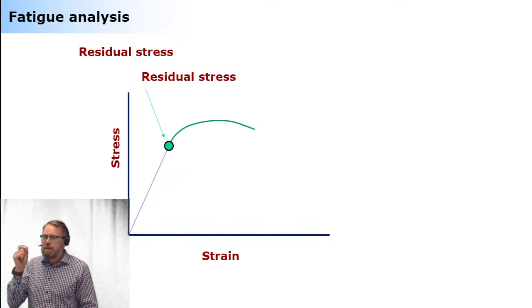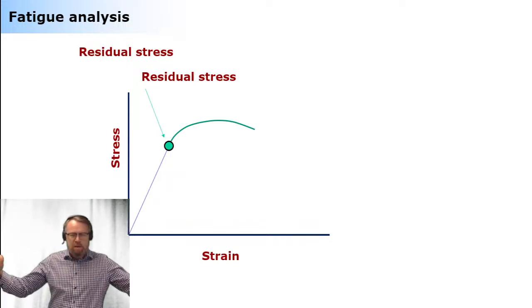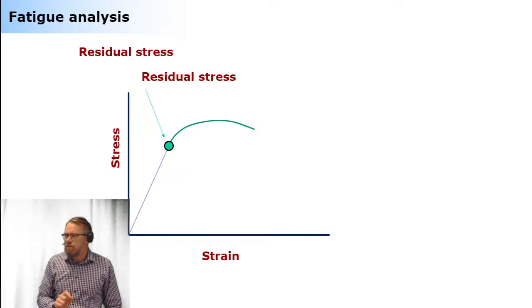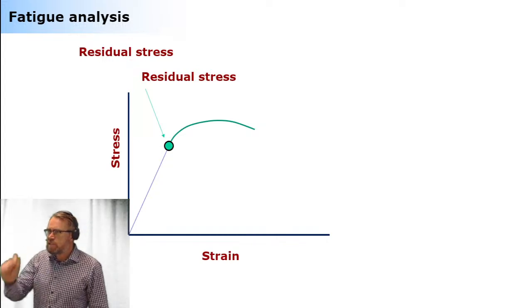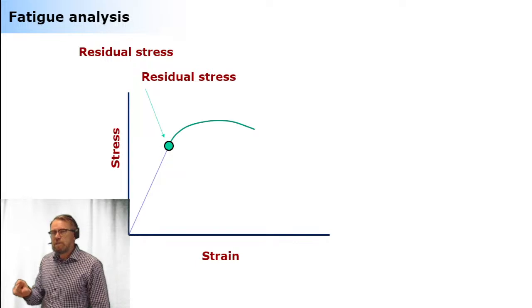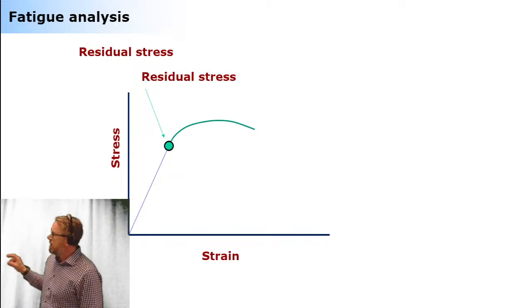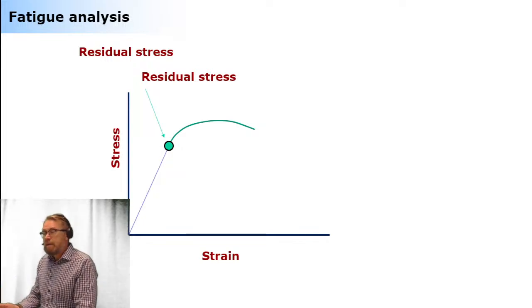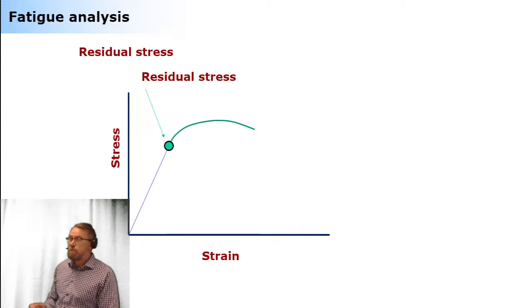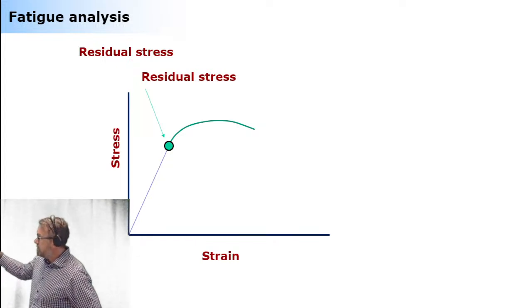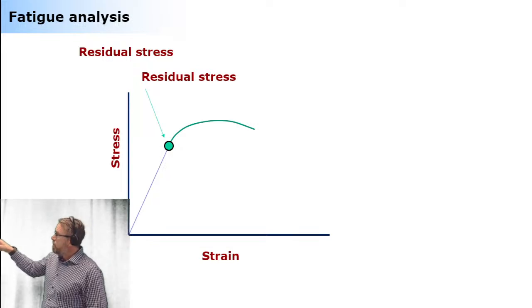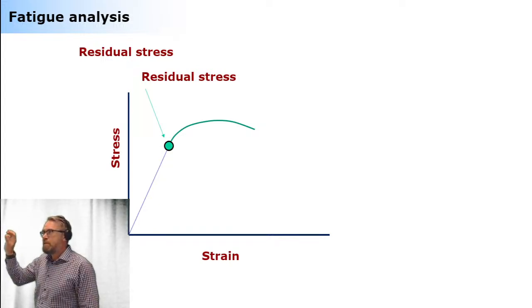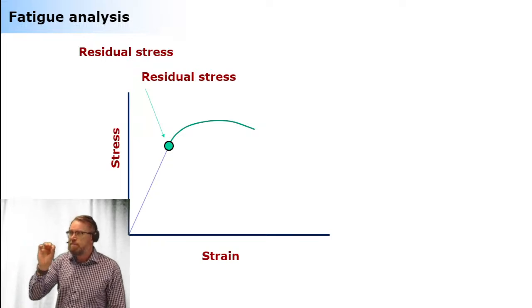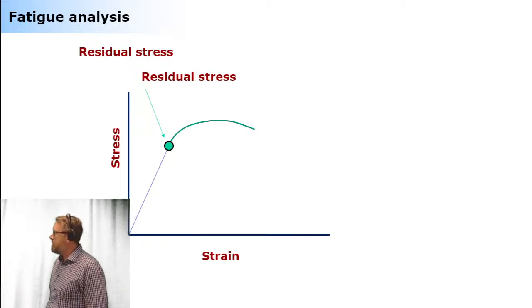Now, very locally, again, let me emphasize, very local, when you're not looking at the structure as a whole, but you look at the minor detail in your structure. Due to the welding process itself, because you're introducing so much heat when you're welding components together, you have very high residual stresses. Actually, in a corner, this linear behavior turns out to be non-linear behavior. And this non-linear behavior is very bad because, let me rephrase it, if you step left from the point that you can see, there's a green spot on my screen, if you step away from that, then you can introduce a permanent deformation. And again, if you have high residual stresses, you can introduce a permanent deformation locally. And this is the situation when you have this conventional steel.